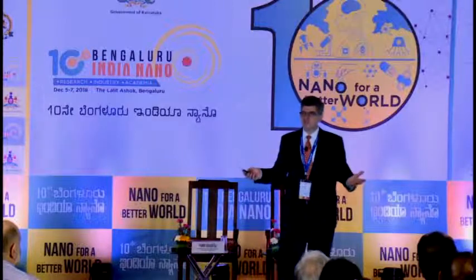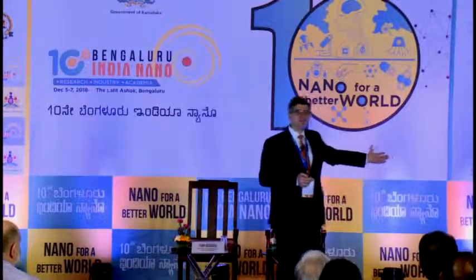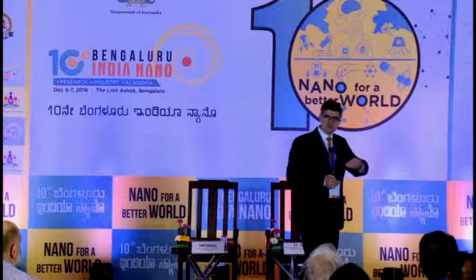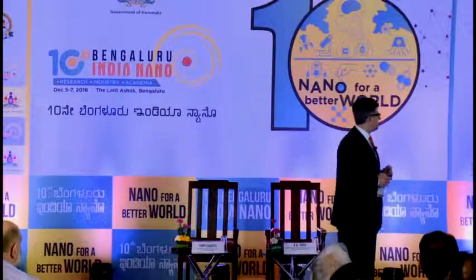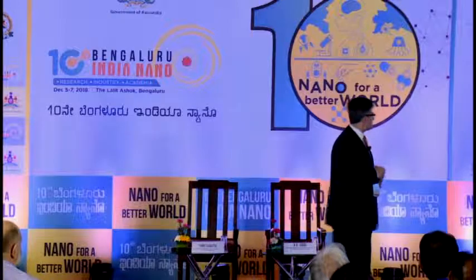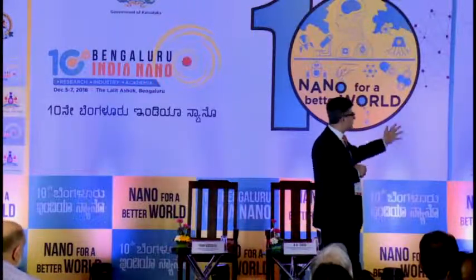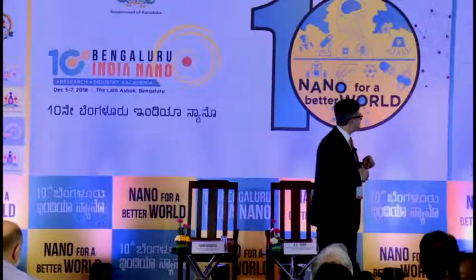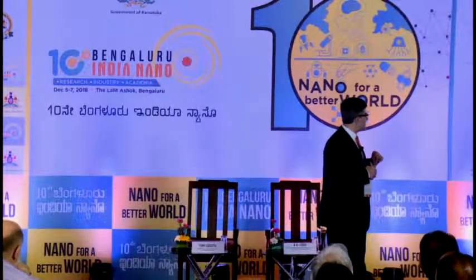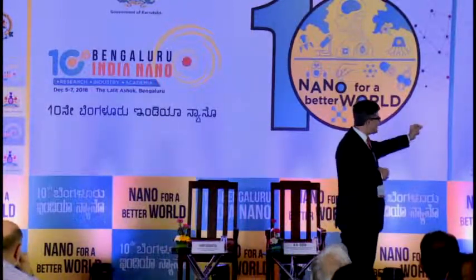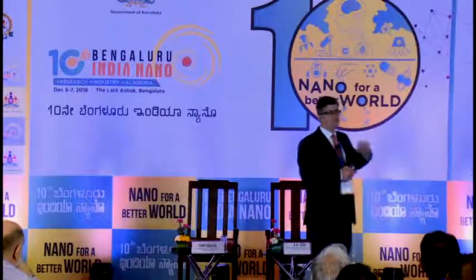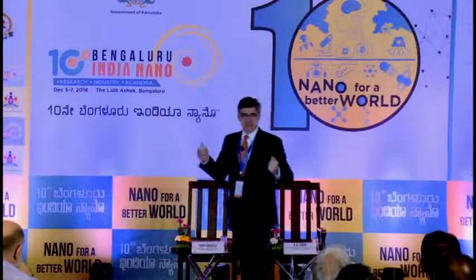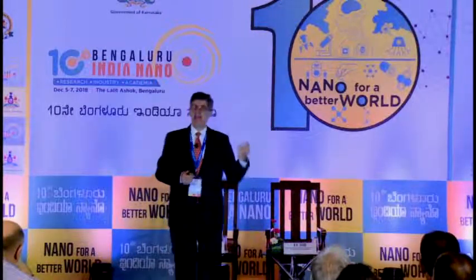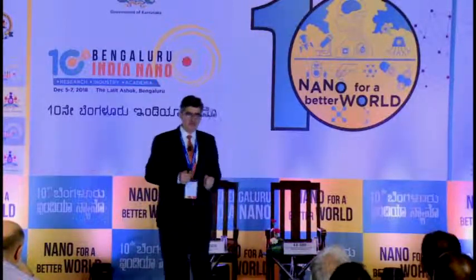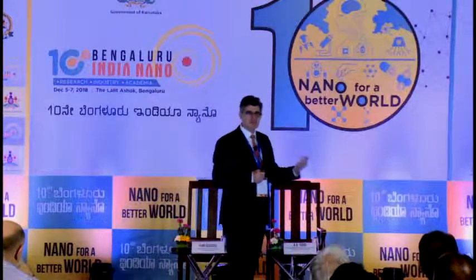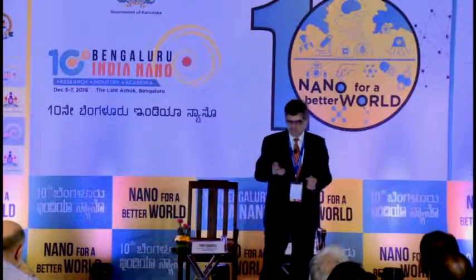What is important? Since we have strong, large flakes, we can, for example, make fibers. We can actually spin fibers. We can gel cast fibers. And this is work done with Australian colleagues on bi-scrolling fibers with loading of about 98% MXenes and 2% carbon nanotubes. You can see we can make a knot on these fibers, and we can really make textile with these fibers. We are working with a colleague at Drexel who does knitting of these fibers into textile, making smart textiles out of it.